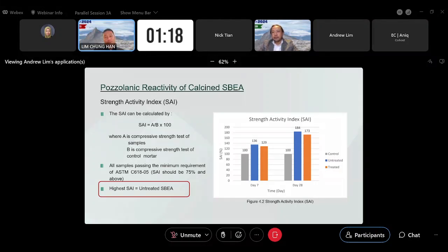Obviously, a lot of pozzolanic materials are waste material, so you want to put in as much as you can to reduce the amount of cement you use. Unfortunately, there is a trade-off, because you want to put in around 20 to 30%. Anything more, the strength will go down. But that is for untreated SBEA. There is another method of treatment, which I didn't cover here, which is grinding, making the particles finer. If you can make it finer, you can actually increase the amount of replacement as well.